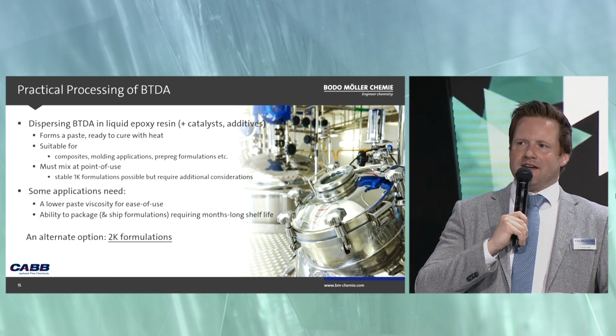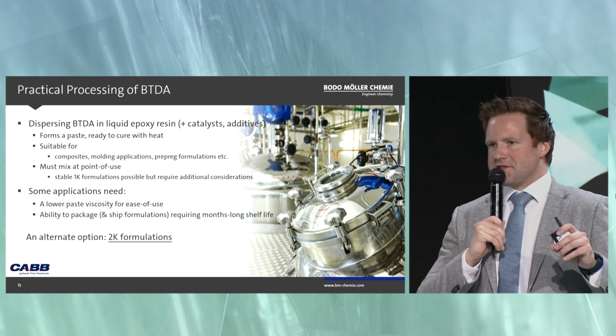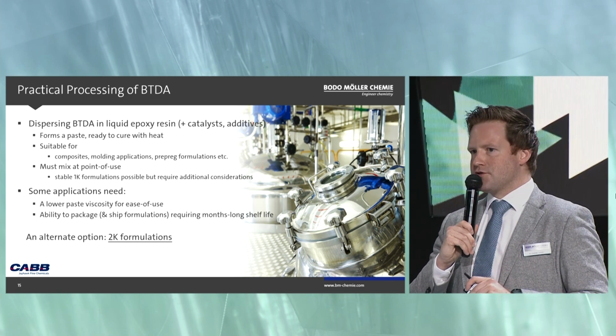But you have to keep in mind that storage stability at room temperature is not perfect, so it needs to be used more or less right away and needs to be mixed in time. But stable 1K formulations are also possible. They need to have different kinds of considerations. Maybe you have to go down a little bit with the storage temperature, but then they should be stable for a longer time. But of course, we also see in the market multiple different applications that have needs, for example, for lower viscosities, or they want a better way of storage stability and packaging.